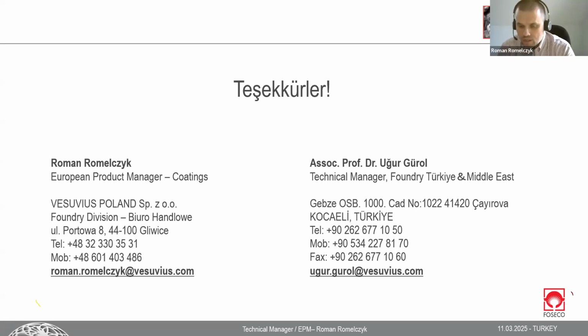One super important point is the right selection of the coating, because as I explained after your question about permeability, if we have a coating with low permeability, the gases which try to push the coating on the surface of the core or mold will be blocked by this low permeability, and the gases will have a chance to remove the coating, explode the coating from the surface. So this is the first point. We have a chance to play with permeability, to select the right coating. This is the most critical.